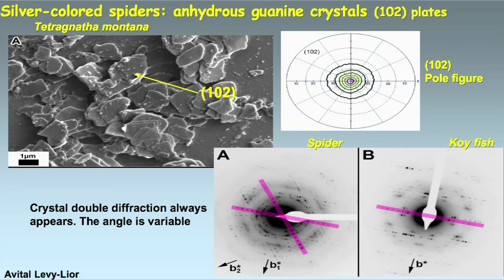So the crystals turn out to be, in fact, the same type of thin plates that develop in the same manner, developing the same large face that we already saw is so useful for achieving high reflectance. And the pole figure confirmed that, and the electron diffraction does. But look what happens here. All the crystals, the single crystals, or what looks like a single particle, give a double diffraction. And then one could say, okay, we know that that's certainly twinning. But no, it's not twinning, because the angle is variable. We have all kinds of angles. So these are two crystals of amorphous guanine that for some strange reason always appear together in doublets.